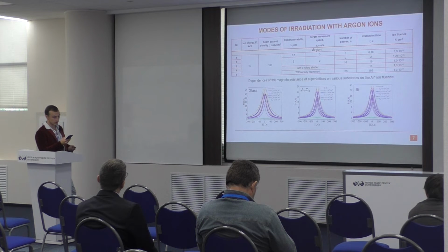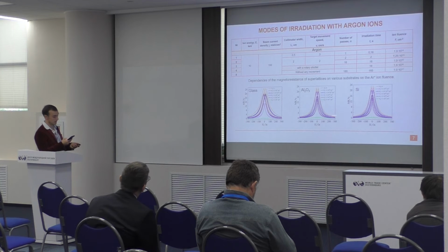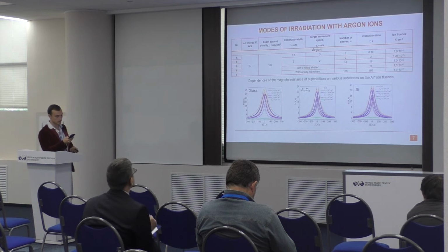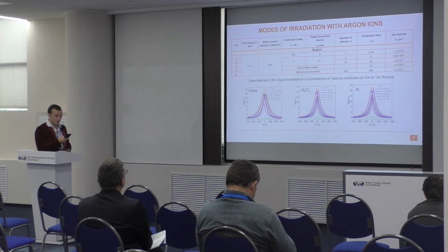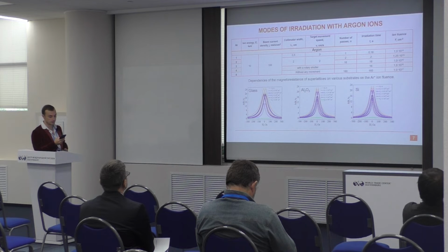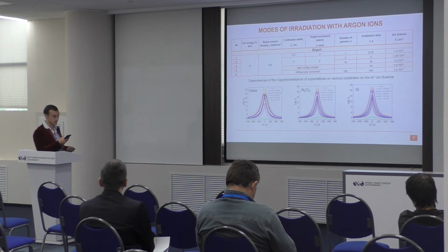At the fluence of 10 to the power of 17, the GMR effect, as shown on the slide, completely disappears. A comparison of the magnetoresistance values after the ion fluence is set in various ways: by a continuous ion beam, and in a pulsed periodic mode using a shutter, when there is no heating of the samples, curves F3 and F4 on the slide.